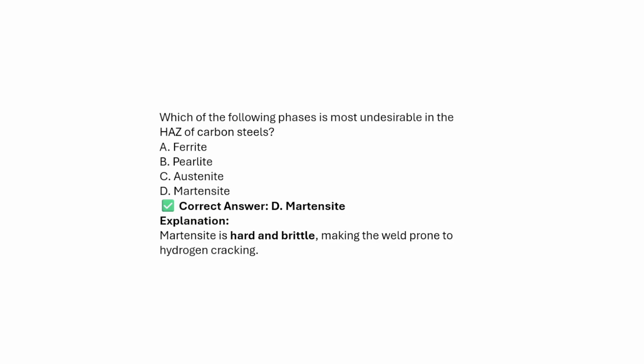Next, which of the following phases is most undesirable in the HAZ of carbon steels? Option A, ferrite phase; option B, pearlite phase; option C, austenitic phase; option D, martensitic phase. The answer is the martensitic phase, because it generally has higher hardness and brittleness. During cooling, the weld metal contracts volumetrically, and because of its brittleness it will break and a crack will initiate. That crack results in the failure of the material. So martensite is hard and brittle, making the weld prone to hydrogen cracking.